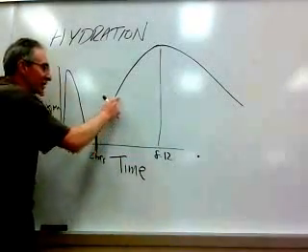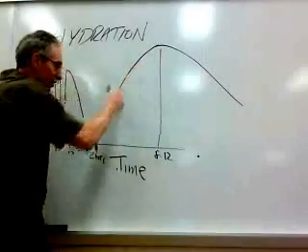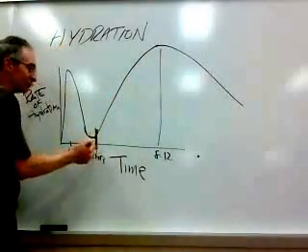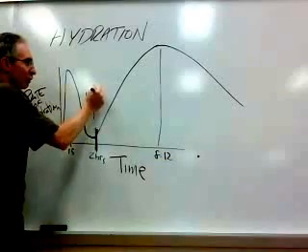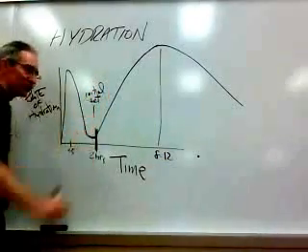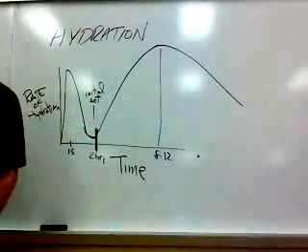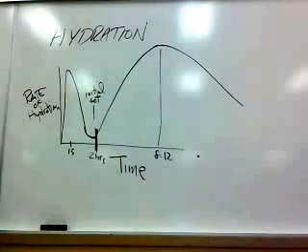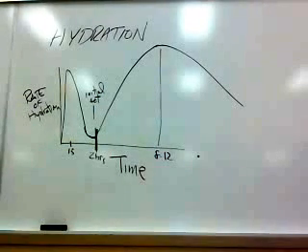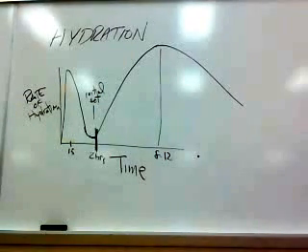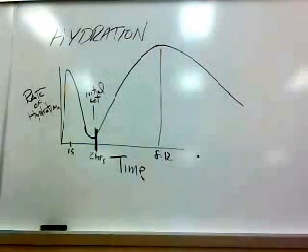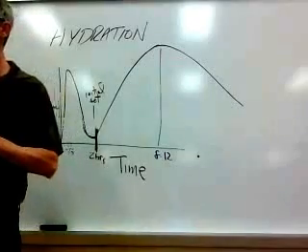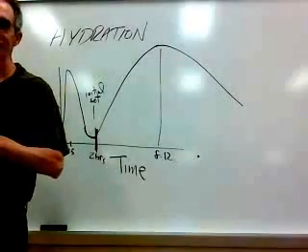because after that point in time, the rate of hydration is going to kick up, and this is where you'll start getting what people refer to as the initial set. The concrete will begin to harden. Okay? It's not hard enough to walk on it yet. It's not hard enough to push a wheelbarrow across it. But you can see it's starting to stiffen up. All right?